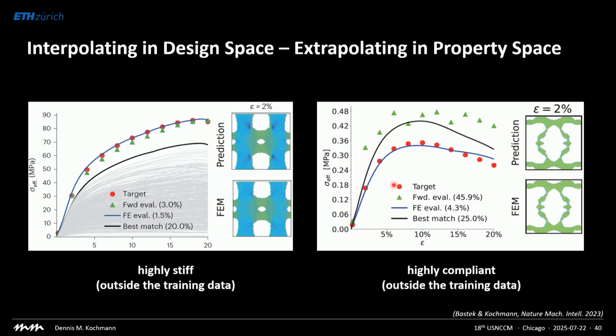We just put pixels in different positions. But that does not mean that we also have to interpolate in the property space, because we can design structures that have properties far outside what we had in the training set. Here, for example, what you see in gray are all the different curves that were contained in the training set. If you now say, give me a structure that is 20% stiffer than the stiffest structure you've ever seen, it can easily do this. If you go to the opposite end and we say, give us a structure that is 20% softer than the softest structure you've ever seen, so if you notice the scale, this is really down here at the bottom, it can also do this.